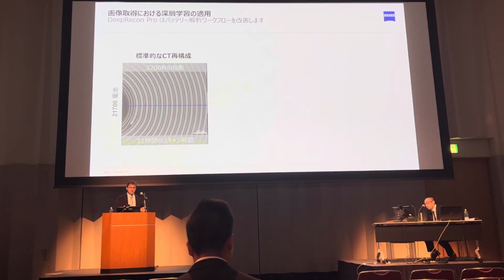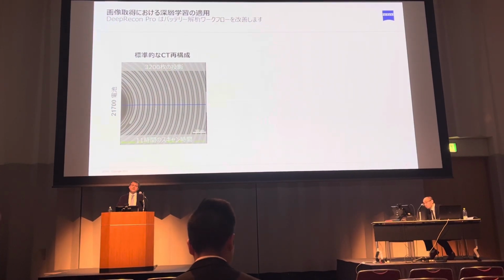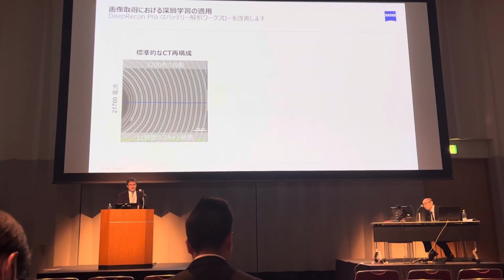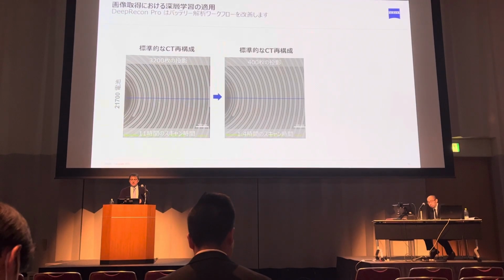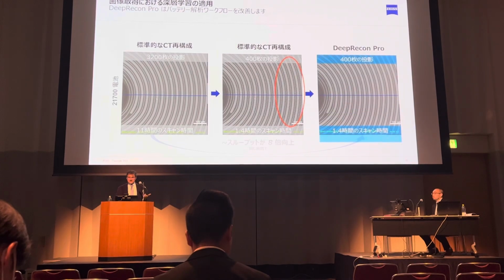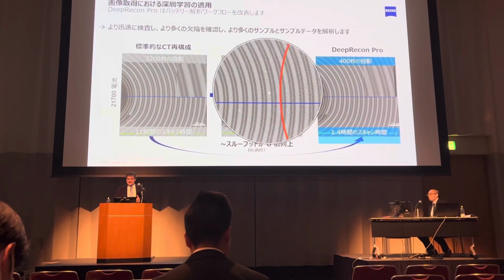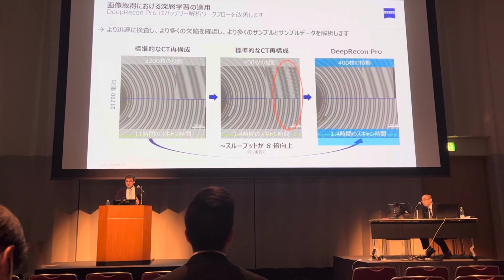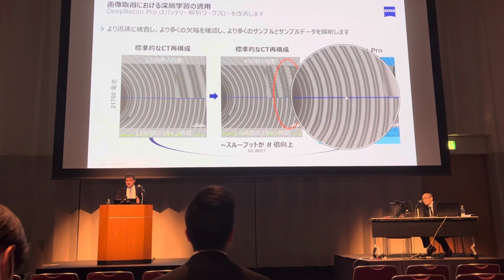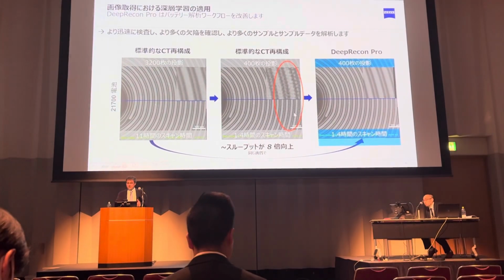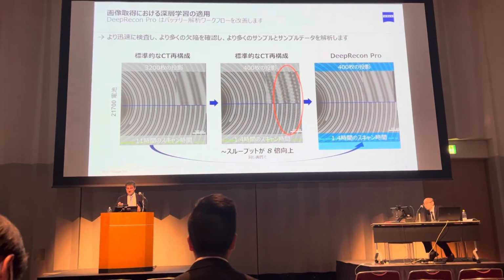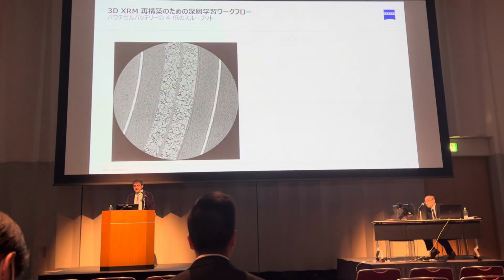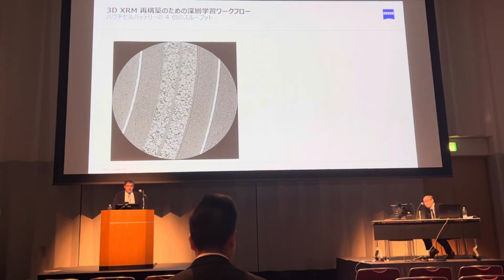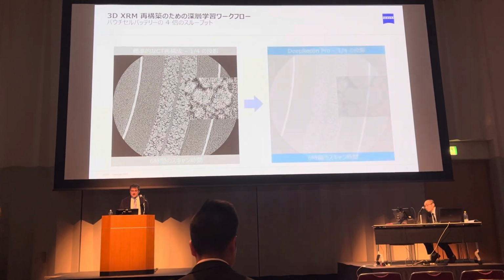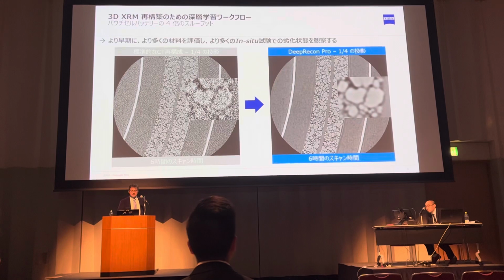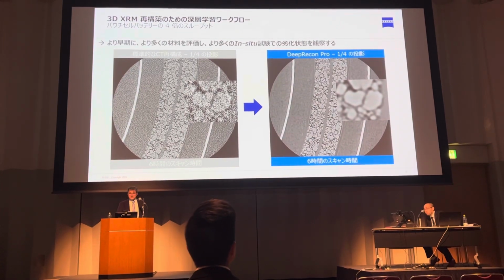And here is an example of a 21700, which to get a good quality image, you need over 3,000 projections. If you reduce the projections, then you start seeing some noise artifacts. This is the standard way of reconstruction. If you use deep learning now, you can use less projections and get the same 400 projections and get great quality image. So you speed up the scanning. Now, if you want to scan now all the way to small details, again, when you start putting the projection in the standard way of reconstructing, you see a lot of noise.